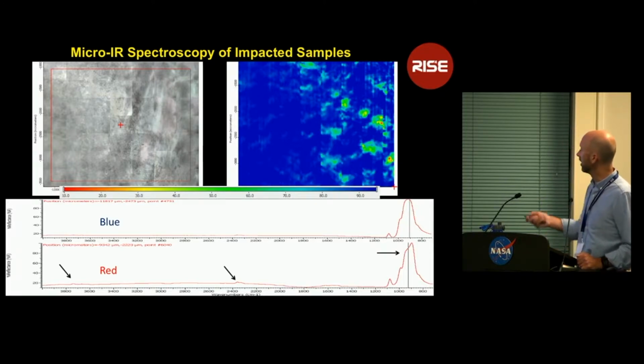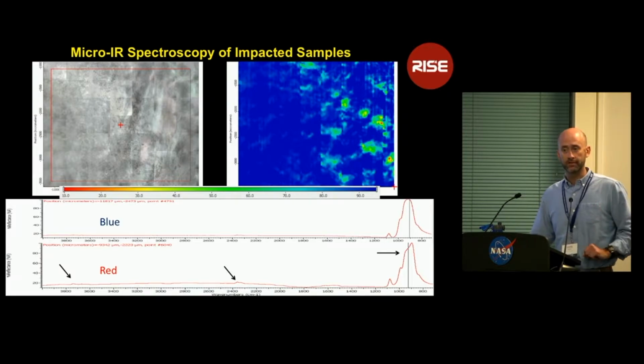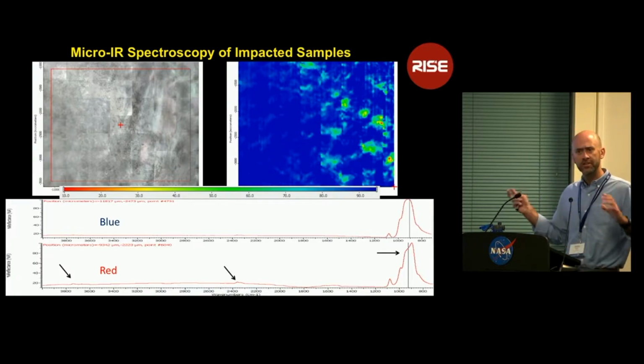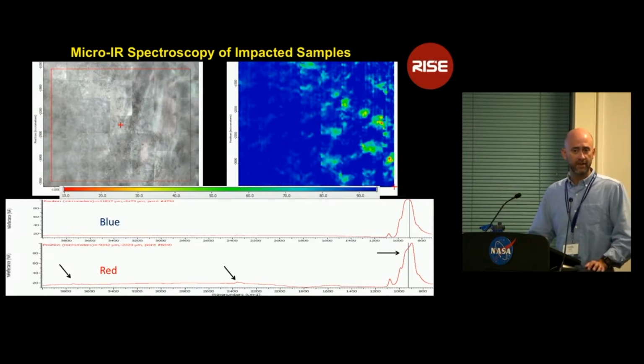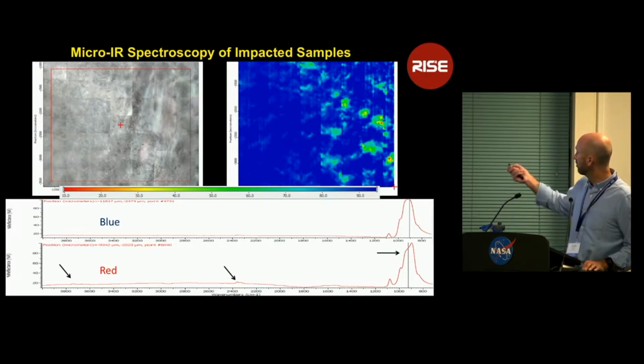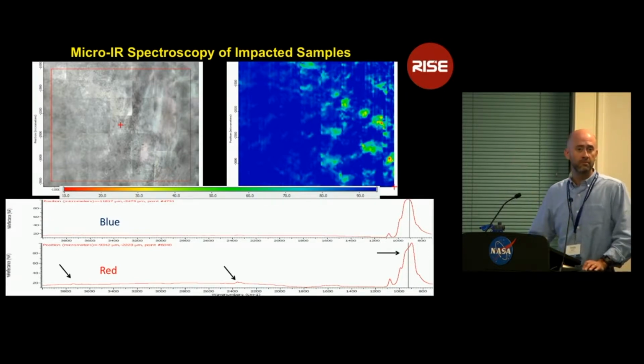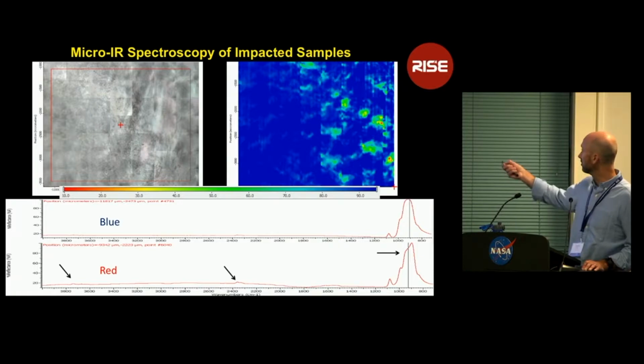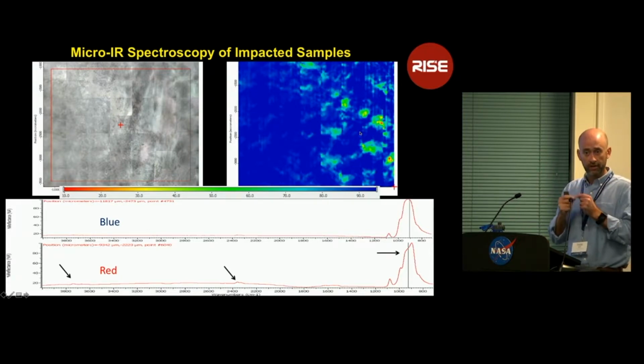incorporated into the sample. I didn't mention that these data are acquired at a spatial scale of 25 microns per pixel. And so our craters are probably close to around 10 microns or so. So our craters are probably less than 1 pixel, but you're certainly seeing damage in the area around these craters that is much more extensive than the individual crater itself.